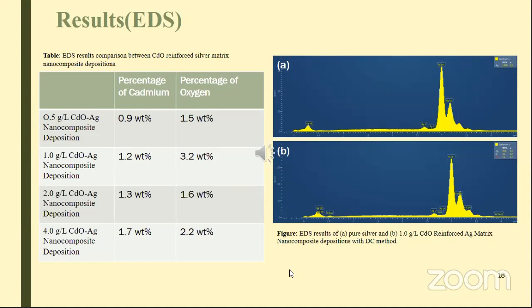From this table, we can assume the percentages of cadmium and oxygen. The percentage of cadmium in the depositions increases with the increasing amount of cadmium oxide. From the figure on the right, you can see the EDS results of the pure silver and 1 gram per liter cadmium oxide silver nanocomposite coatings.